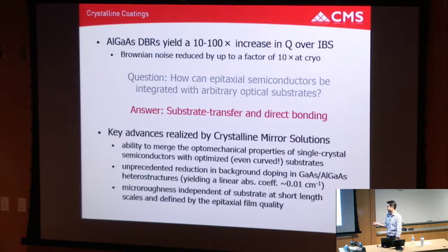The key advances by myself and now by CMS were really the ability to merge these high-quality single crystal materials onto arbitrary curved surfaces. One thing that's turned out to be lucky was I had some concern early on that every time I switched substrates, I'd have to totally change the process, so bonding to fused silica versus silicon versus YAG or something. But it actually turns out it's very small tweaks to the process, which is nice, because in the end, I want it to be just as flexible as direct deposition.